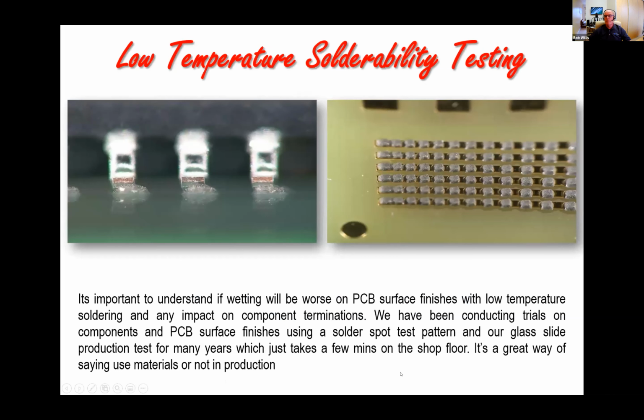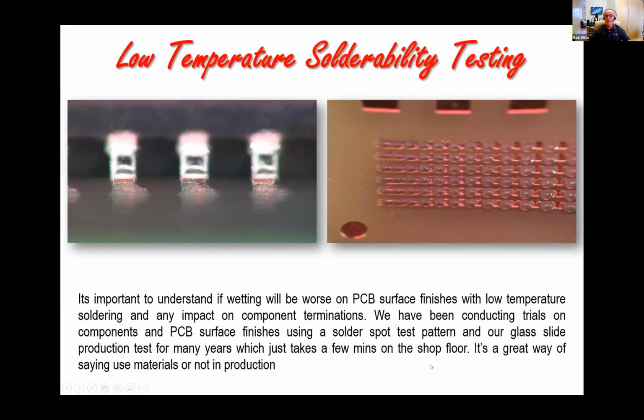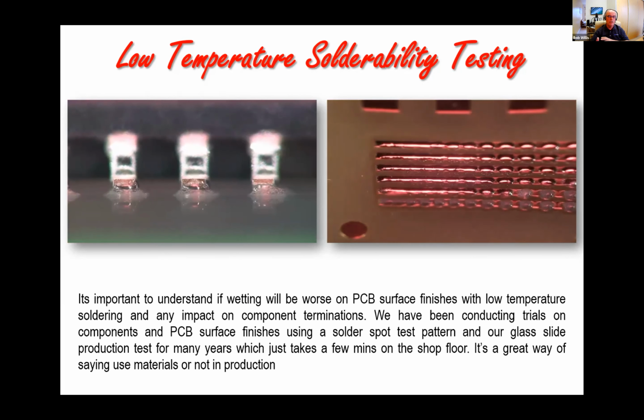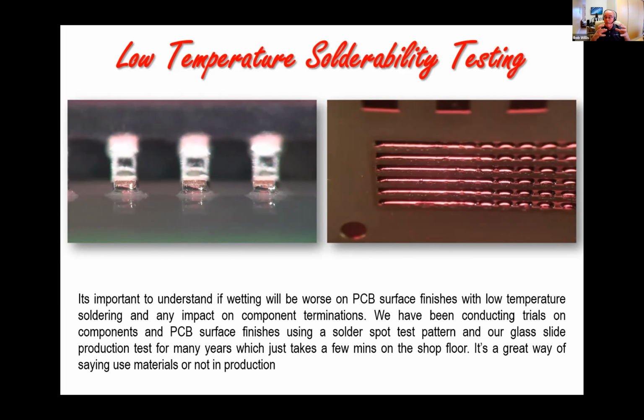Now, solderability and wettability is something we still need to understand with these low temperature materials. I don't really think there are too many problems, but I always like to highlight things that people forget about. And if you take a solder paste and you modify the type of fluxing system and the temperature that it actually activates at to start the soldering process off, what are the consequences? Well, consequences can be wettability and solderability of components and PCBs. So I've done a whole series of trials on different surface finishes with wetting indicators that you see on the video on the right-hand side, and reflow trials on all the quite common surface mount joints, just to see the wettability and solderability and how they change with these materials.